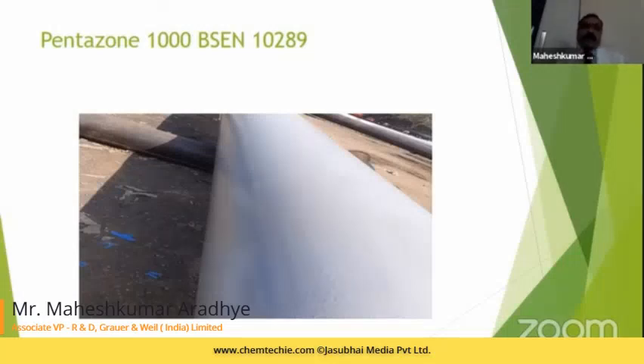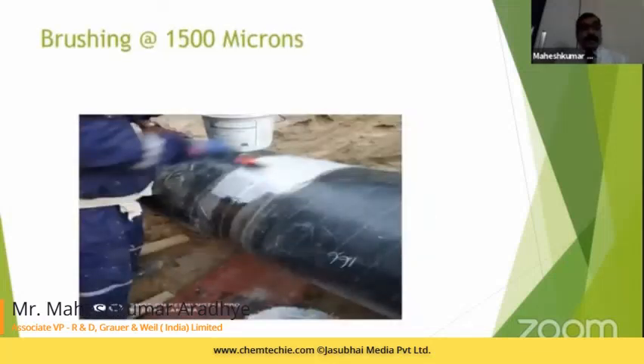This product can be applied by single leg airless spray or plural component airless spray, for thickness requirements from 400 microns to 1500 microns. As you will see, the whole pipeline here is coated with Pentazone 1000 BS EN 10289. In this case, the thickness requirement was a minimum of 800 microns. Pentazone 1000 BS EN 10289 is giving the service as per type 2 class B. Here you could see it is applied by brush onto the hand tool prepared surface. This is the classic example.